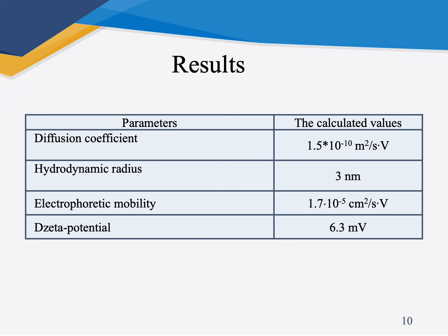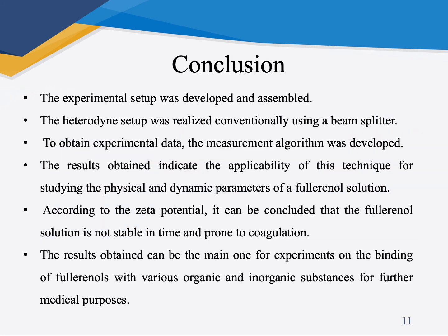The obtained parameters can be seen in this picture. The main conclusions of our study: the experimental setup was developed and assembled for dynamic light scattering measurements, and the heterodyne setup was realized using a beam splitter. To obtain experimental data, the measurement algorithm was developed. The results obtained indicate the applicability of this technique, and according to the zeta potential, it can be concluded that the fullerenol solution is not stable in time and is prone to coagulation. The results obtained can be a basis for experiments on the binding of fullerenol with various organic and inorganic substances for further medical purposes.